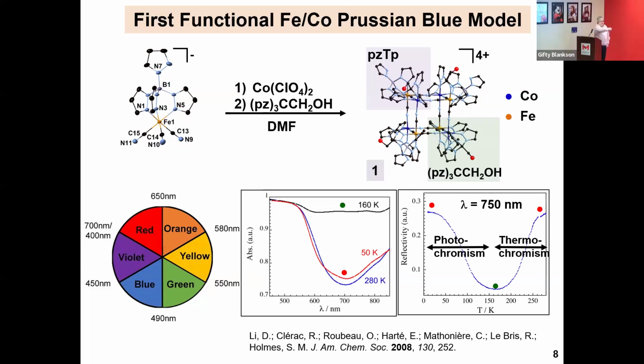It was red at high temperature. That's where we have the iron 3, cobalt 2 pairs. At low temperature, around here, it becomes green. That's where we've done the electron transfer and we have iron 2, cobalt 3. But the light shining on the sample causes the electron transfer again as you get to colder temperature. Then it becomes red again.